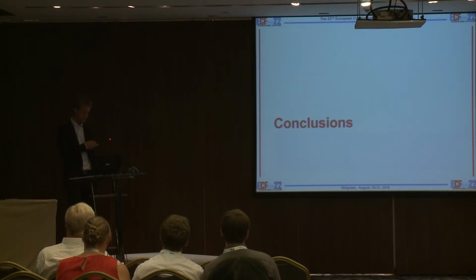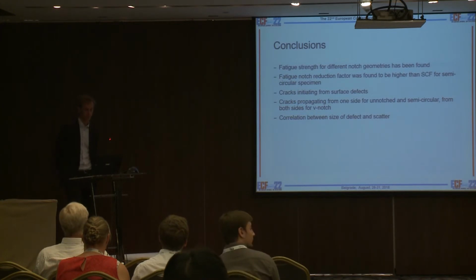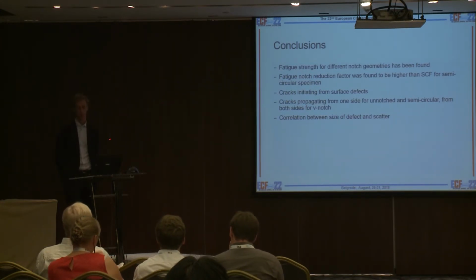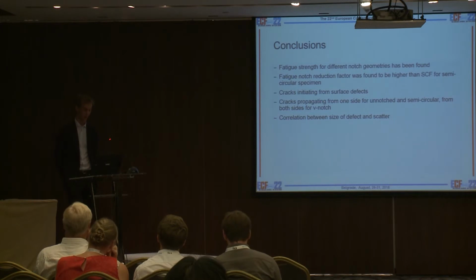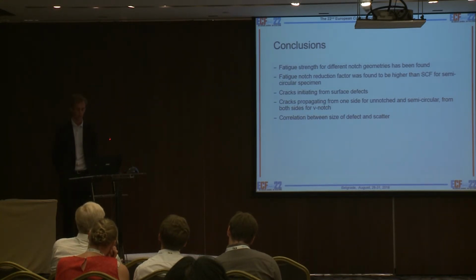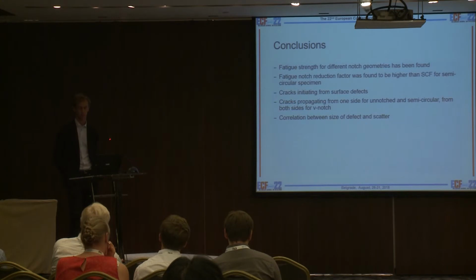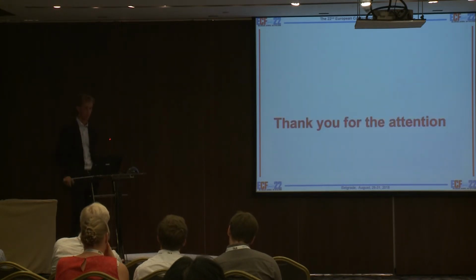Okay, so we have looked at the fatigue strength of different notch geometries, and this fatigue notch reduction factor was found higher than the stress concentration factor for the semicircular specimen, which is very weird. Cracks initiated from surface defects in all specimens, and the cracks propagated from one side in the unnotched specimen and the semicircular specimen, and from two sides in the V-notch. And also the correlation between the size of defect and the scatter has been found. Thanks for your attention.